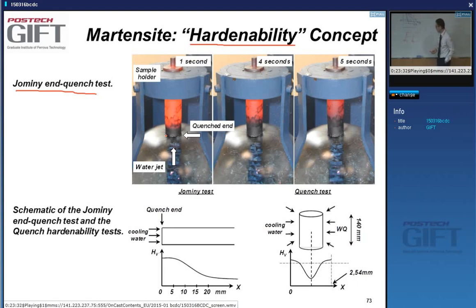However, if I have a steel, so again, room temperature here. And I have the same cooling rates. This cooling rate at this point and this much lower cooling rate, yes, at this point, yes? But the steel I'm using has different transformation kinetics, has a different TTT diagram. And for instance, it has this TTT diagram. The transformation, the decomposition reaction, the C curves for the decomposition are on to the right. Yes. So as a consequence, with the same cooling rates, I will get martensite here, and I will get martensite there. So we say this steel has a higher hardenability than this steel. Yes.